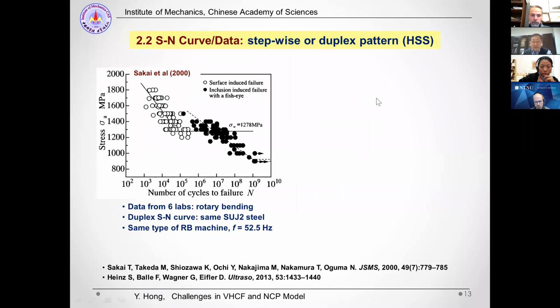That's the first point, and then I will mention the second point, the SN curve. These are the data from a kind of round-robin test organized by Professor Sakai. The left part is the crack initiation from the surface, where surface crack initiation causes the fatigue failure, and the right part is from internal crack initiation.